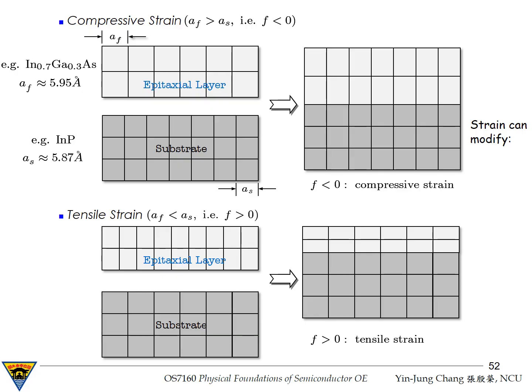An example shown on the slide is indium 0.7 gallium 0.3 arsenide grown on top of an indium phosphide substrate. A sub f is approximately 5.95 angstroms, while A sub s is about 5.87 angstroms. Since the film lattice constant is larger, the film must be compressed laterally to match the substrate. When this happens, the lattice spacing in the direction perpendicular to the interface, which is in this direction, usually expands slightly. So we see that the height of the lattice shown here is slightly larger than that right here.